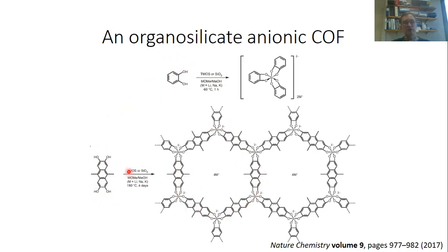So again, you can start out with tetramethoxysilane or silicon dioxide, and you react these silica precursors with a ligand in methanol in the presence of a base, which again can be lithium, sodium, or potassium methoxide. In order to crystallize this framework, you need pretty harsh temperature conditions. So in order to make the molecular anion, 60 degrees are enough. In order to really crystallize such a framework material, you need 180 degrees Celsius for 4 days. So this reaction here proceeds all in 1 hour, as you can see. For this reaction here, you need 4 days. And that's because we constantly have to make our framework self-repair so that it can actually crystallize.